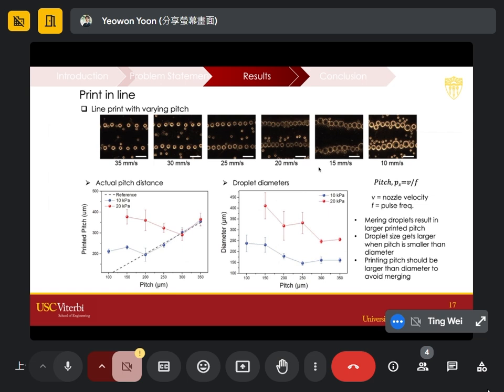As it turns out, X is the design pitch distance, and Y is the printed pitch distance. You can see after some point, the printed pitch distance deviates from the reference point. That means droplets started merging. And on the right bottom figure, if the pitch distance decreases past some point, you can see the error bars increasing with the diameter. That also indicates droplets are merging, becoming one bigger droplet. So here, we learned that the printing pitch of 2 droplets should be larger than the diameter to avoid merging, and that forces us to print within the critical pitch distance between 2 droplets.